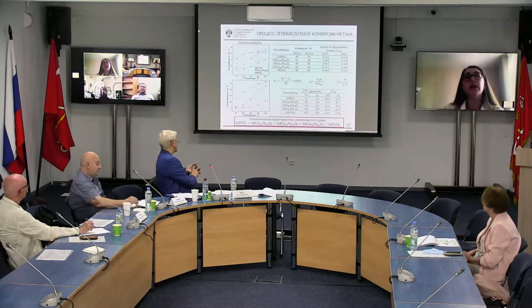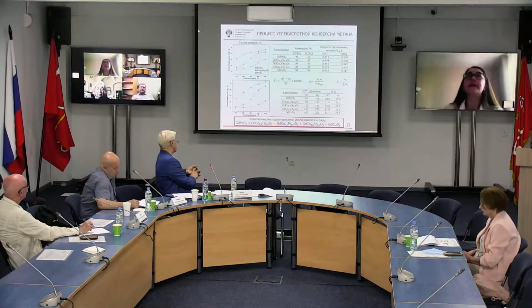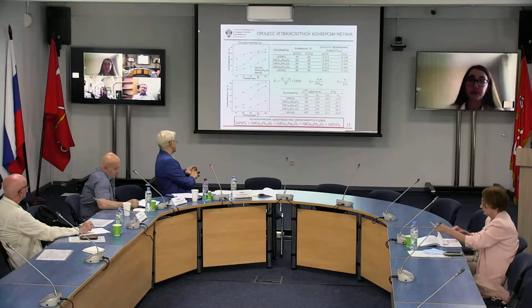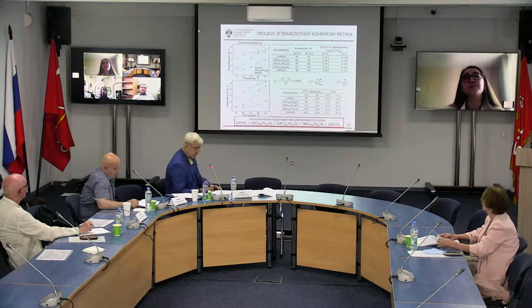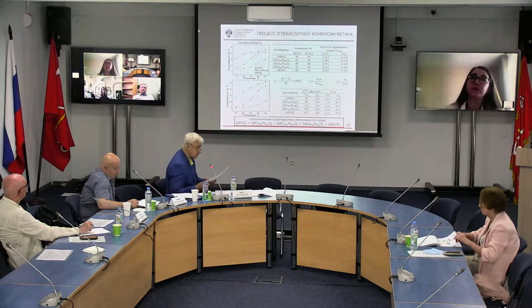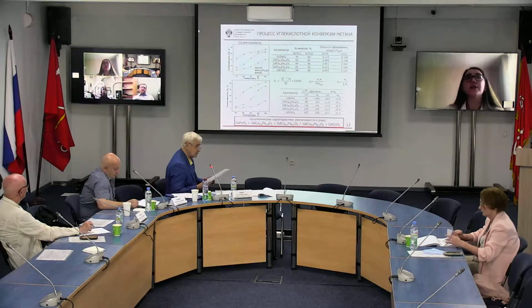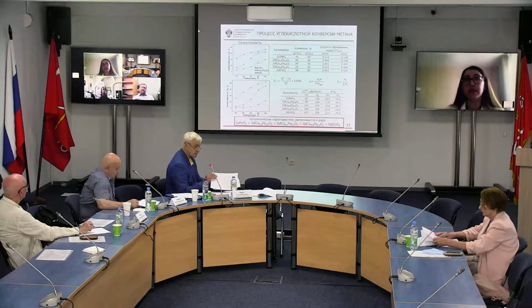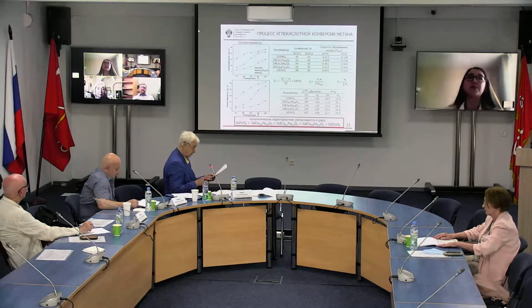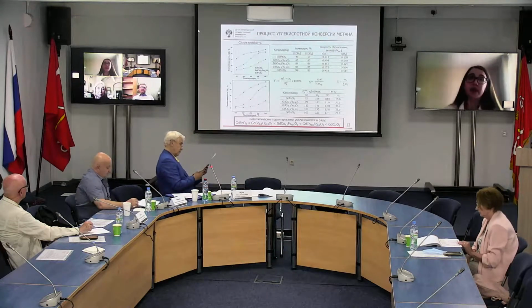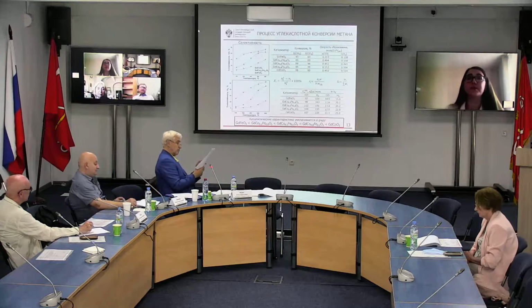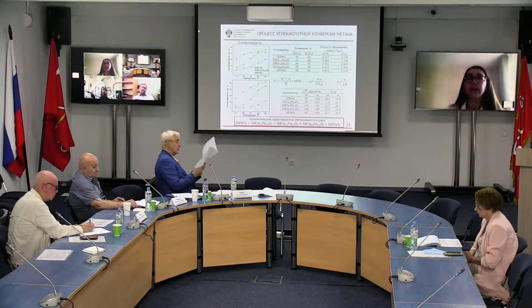And on the next slide you see the results of the study of catalytic characteristics of cobalt-substituted ferrites in dry reforming of methane at 750 and 950 degrees Celsius. Regardless of the fact that for all compounds the catalytic characteristics grew with the rise of temperature, we observed certain differences in catalytic characteristics of perovskite-like oxides.